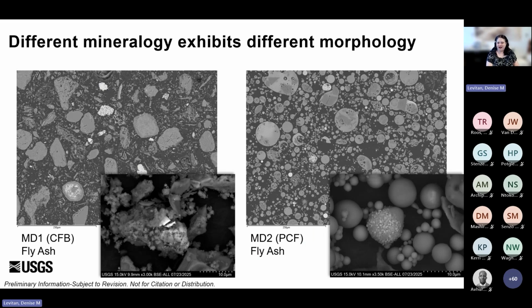So we also have some photomicrographs, pictures taken on the scanning electron microscope that I think illustrate this a little bit more visually. So on the left is MD1, and you can see there's a lot of variation in particle size, but also in particle shape. You know, you see some rounded particles, some flaky particles, some that really don't have much of a shape, all kinds of different morphologies. But then if you look on the right in MD2, the sample from the PCF, it's pretty much all round. You see most of these particles are spheres, and they can be hollow or they can be filled. You can see some kind of hollow structures here. But like I said previously, this is the shape that you get when the minerals melt, form some kind of melt, and then fall and cool quickly, forming these little droplets that are spherical shaped.